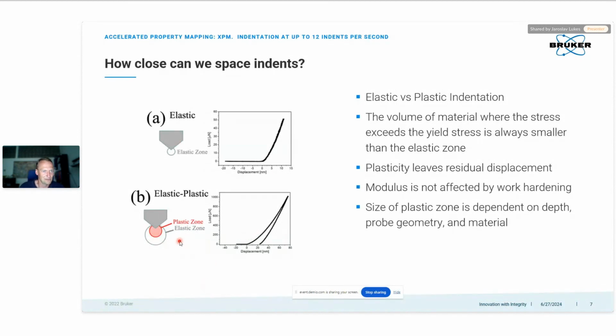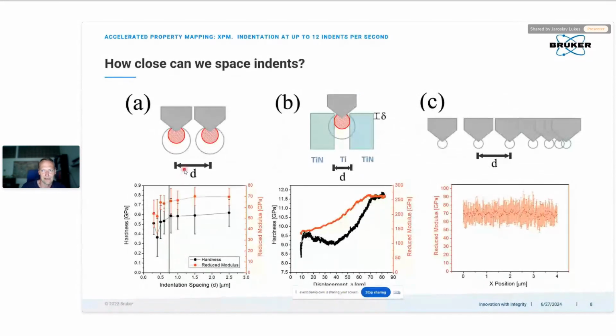That's one thing that you have to take into consideration, and you have to keep the separation large enough to prevent any influence of the neighboring indents, right? This plastic deformation zone should not be part of the plastic deformation zone of the previous indent next to it. These images describe what I just explained. I would say the deformation zone is a function of tip radius and the material itself. The best way is to make a test and measure the influence, and then you can decide what the separation should be. Otherwise, there are some rule-of-thumb values that you can apply for different types of materials.